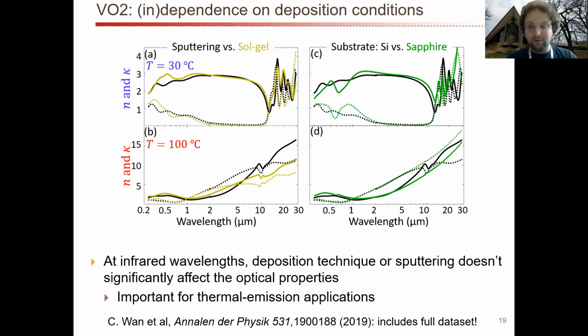And so we partnered with a number of folks at Purdue and Sherman Ramanathan's group at Physical Sciences Incorporated, and we synthesized VO2 in several different ways, several different thicknesses and different substrates using different techniques, and we characterized all of these materials, all of these thin films, from the UV to the far infrared as a function of temperature, and we found something quite interesting. If you look at the far infrared, so kind of beyond about 11 microns, then pretty much whenever you deposit a new film, if you use a different substrate, or if you deposit a different thickness, or if you sputter versus you do sol-gel synthesis, your results are not going to be that different despite all of these optical phonon resonances over here that are very, very sensitive to the material, to how it's deposited.